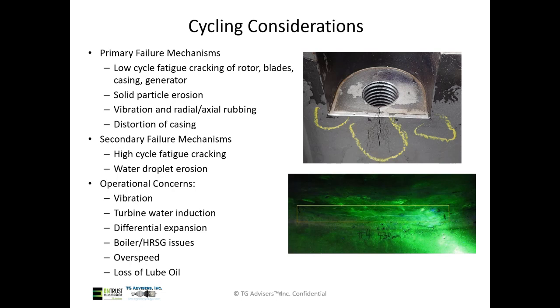The second thing that's happening is we're going from cold temperatures or from lower temperatures to a very high temperature. So we also have thermal stresses for all parts, whether they're rotating or stationary components. So doing this a number of times eventually leads to what we call low cycle fatigue cracking, or essentially cracks forming in rotors, blades, casings, generator components, you name it. They're all exposed to stresses. We can also see stuff like solid particle erosion. Essentially, that's particles that are kicked up from the boiler, the HRSG, when you're cycling, and they're sent through the inlet of the steam turbine, causing some solid particle impact damage that wears away surfaces over time.